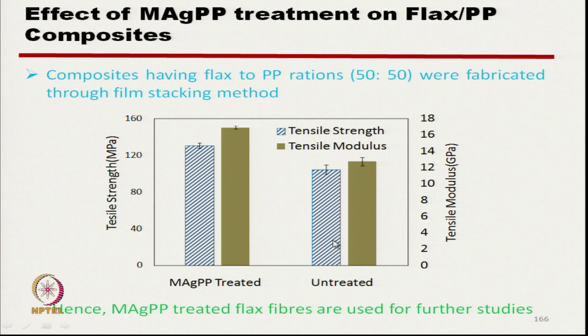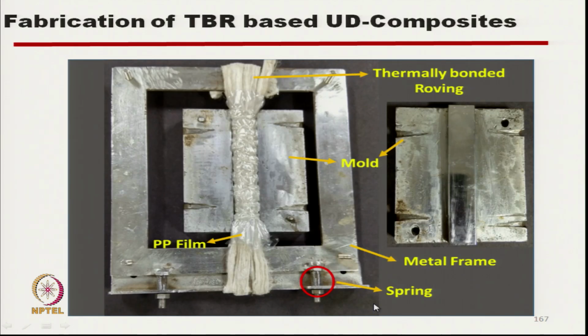If we see the graphs here, for the MAGPP treated composite and untreated composite, both tensile strength and tensile modulus of the treated composite are higher than the untreated. So, for further studies, we have used the treated flax fiber composites. MAGPP treated flax fibers are used for our further studies.